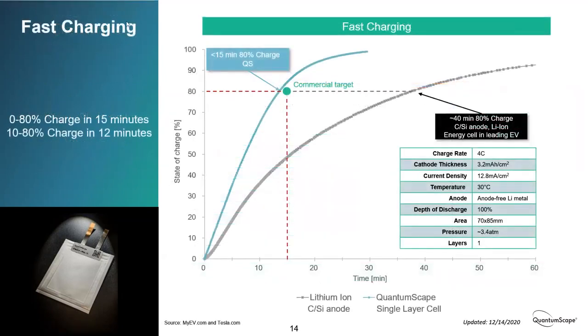So that's cycle life. I mentioned fast charge. I think it's equally important that with the high energy system, we can also charge it quickly. Here is some data that shows how the solid state system charges. For reference, I have this gray curve, and this shows the rate of increase of the charge versus time. This is an example from a state-of-the-art BEV from the last year or two. What you see is going from 0% charge to 80% charge takes 35 to 40 minutes.